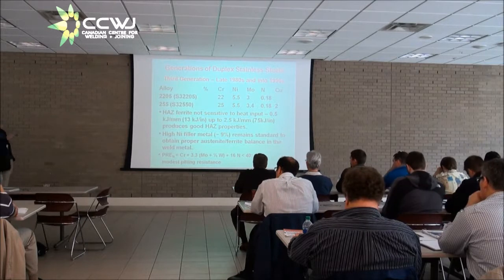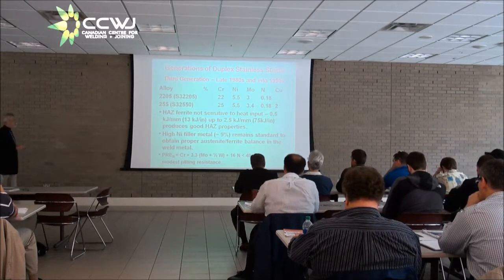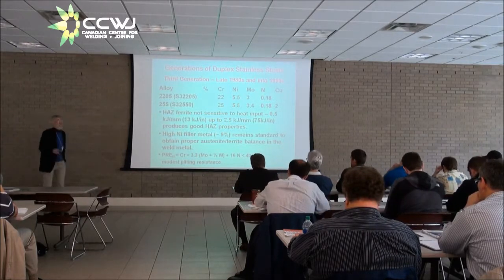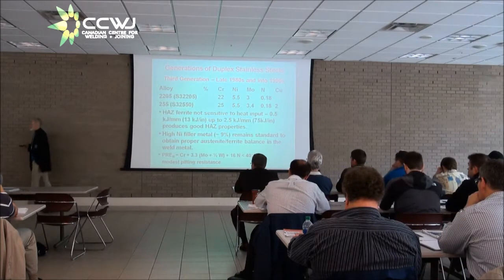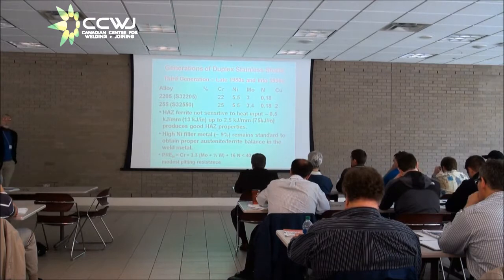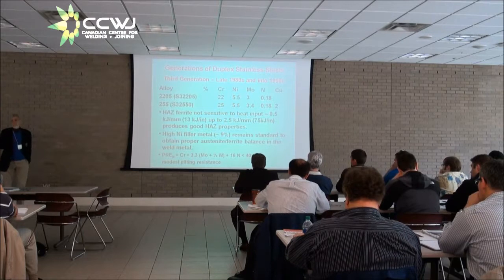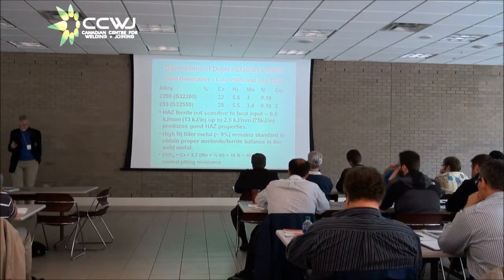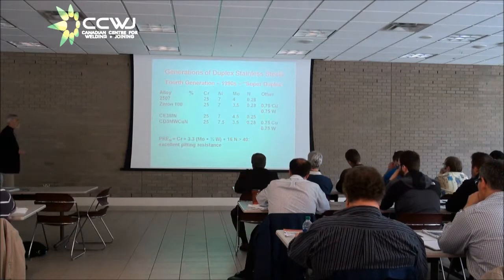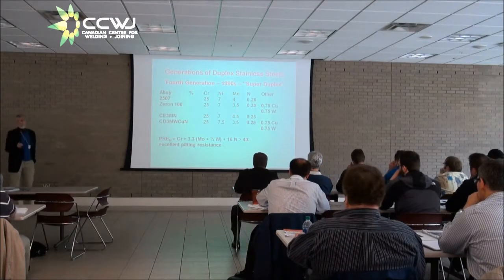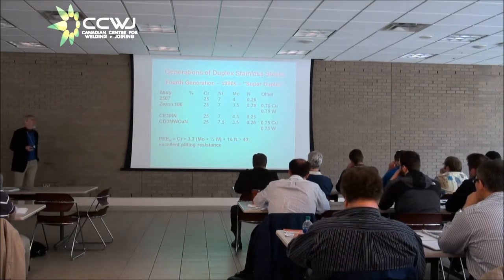So the third generation of duplexes have rather modest pitting resistance. They've got pitting resistance index numbers in the low to mid-30s. What you would like is to get up to 40 because then you can be competitive with the so-called superaustenitics. These are the alloys of 20 chrome, 25 nickel, like 254 SMO or AL6XN. And that brought us to the fourth generation of duplex stainless steels.